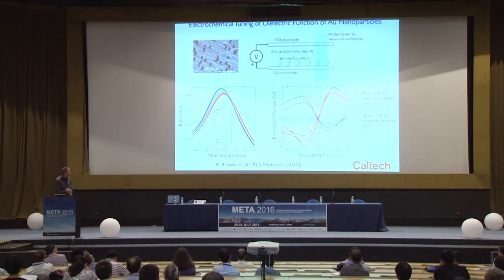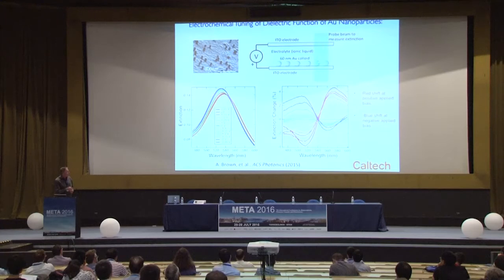And in fact, we can do this, for example, by putting metal nanoparticles in an electrochemical cell. And in order to do this, because of course the intrinsic carrier density of the metal is very high, in this case in the 10 to the 22 range, we have to be able to go to an environment that applies a very large electrostatic charge. And to do this, we use an ionic liquid in an electrochemical cell.